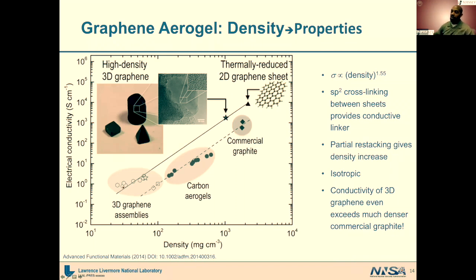And what we've shown here is, if you can actually densify this, we were able to densify a graphene aerogel to about 1 gram per cubic centimeter. You can actually stay on the line of what you would expect for thermally reduced, like an actual sheet of 2D graphene. So this was exciting for us because it was showing that we're actually able to see some of the properties that typically you only see at the nanoscale, but we're actually able to see them at the macro scale in something that you could actually handle with your hand, and build into, or incorporate into, a large scale, macro scale device.